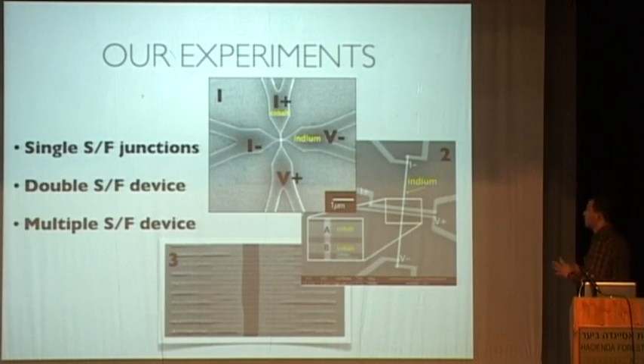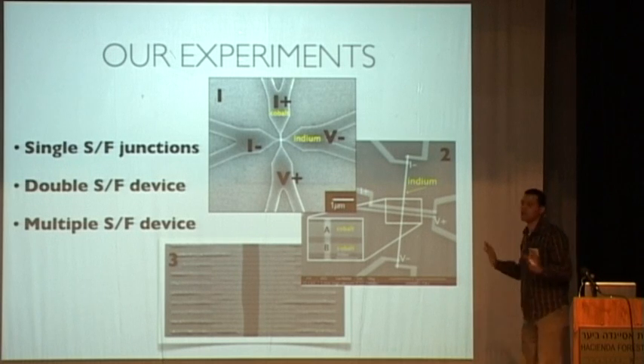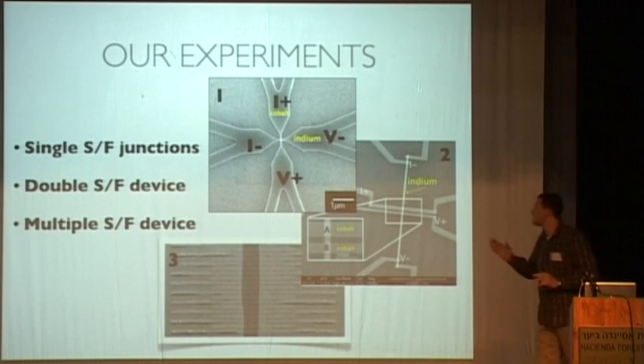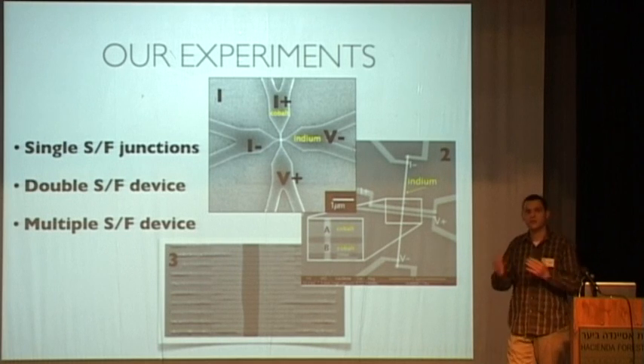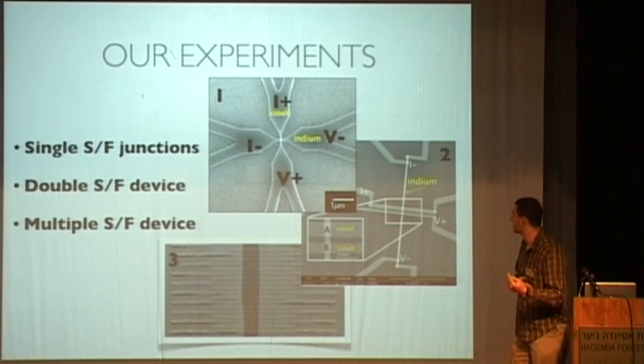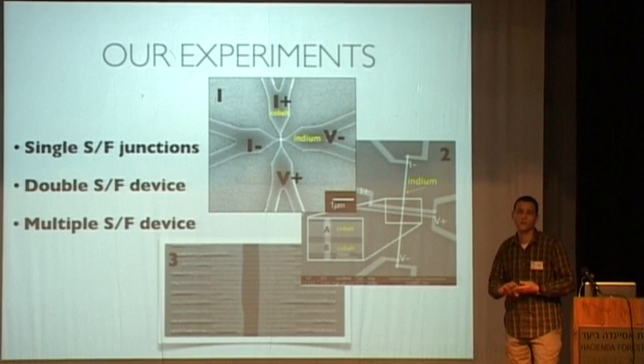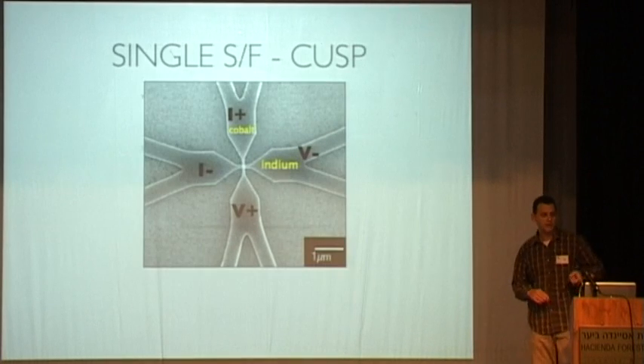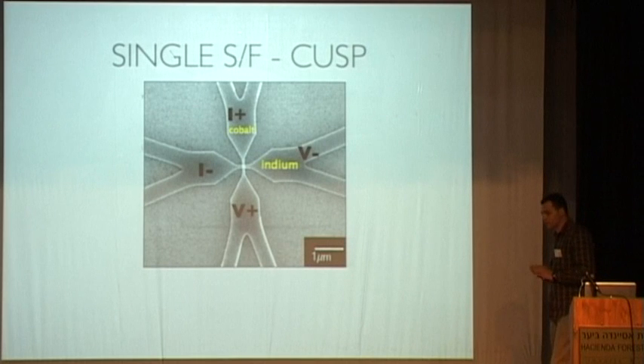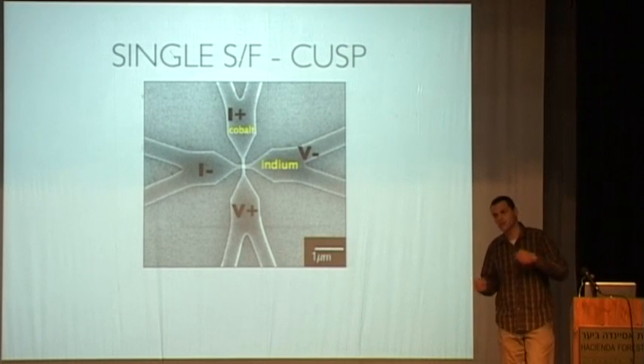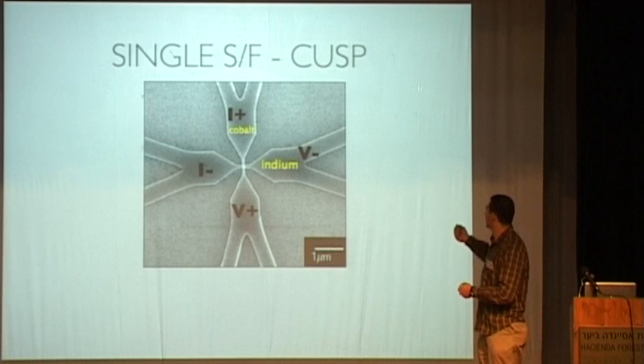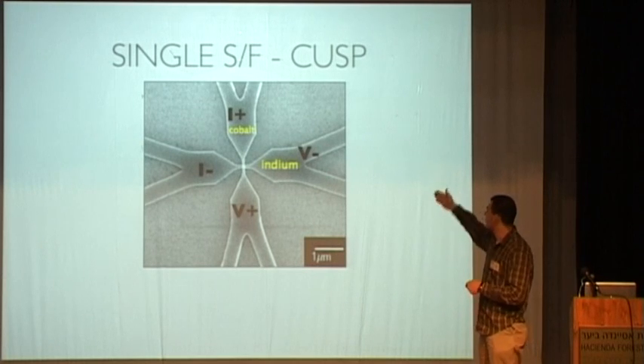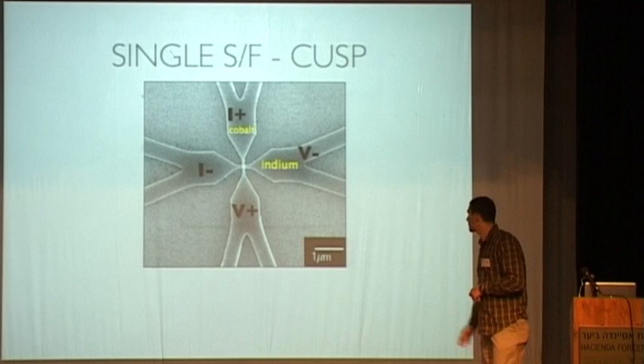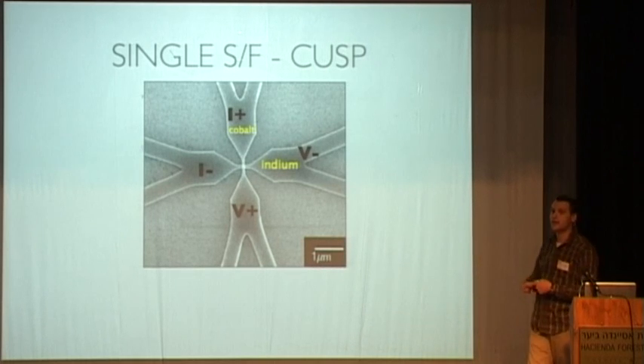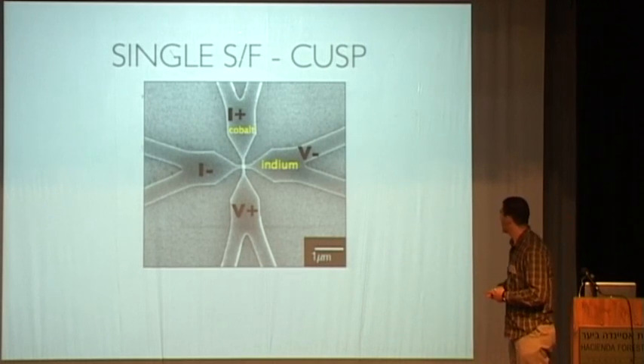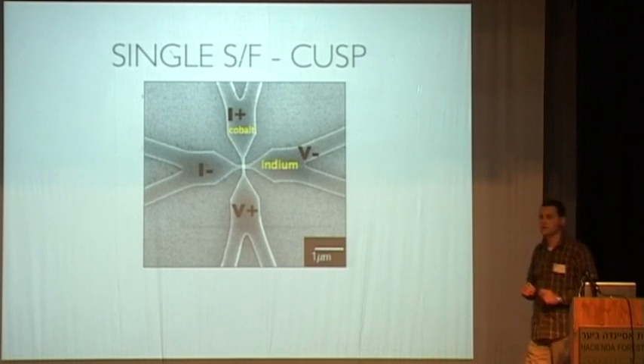So let's go down to our experiments. I will introduce 3 experiments very briefly: single junction conductance between superconductor and ferromagnetic, single junction, double junction, and multiple junction. Now, the first is a very simple cross geometry, which basically means that we inject electrons from ferromagnetic, in this example it's cobalt. You see the vertical line, it's cobalt connected with a superconducting indium. And we measure the conductance of the junction.